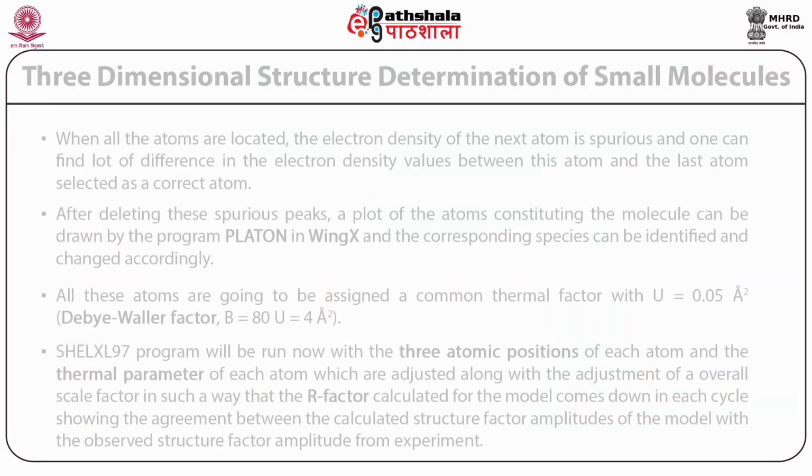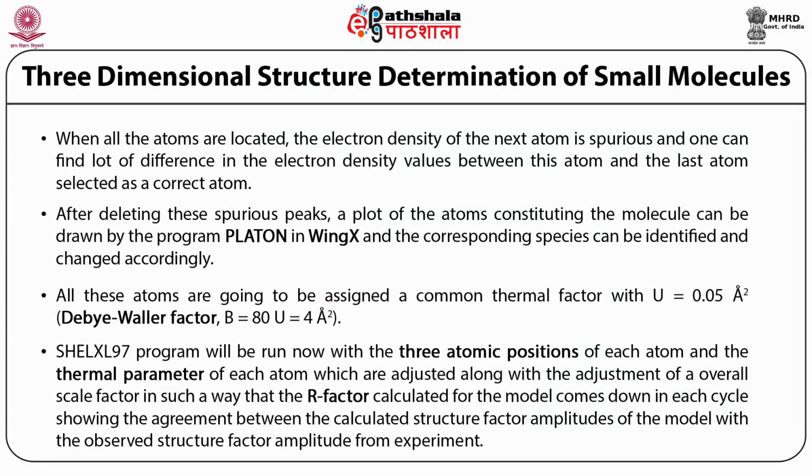Here we are assigning the thermal factor. Even though the assumption made by Hauptman and Karle is non-vibrating point atoms, once the structure is obtained by them, you can assume a thermal factor of 0.05. Even though you give an equal thermal factor for all the atoms, depending upon the neighborhood atoms, some atoms may vibrate more, some atoms will vibrate less. So now with this modification, one can submit the job for SHELXL. Whenever you have the model, the coordinate SHELX file can be used as a plotting program by using the program PLATON available in WinGX.